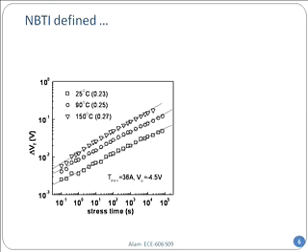Now, why did its threshold voltage change? Because as the hydrogens are diffusing away, you have more defects. Those more defects are catching more electrons. That causes a QF. Do you remember the QF and QIT? So it increases the QF and QIT. As a result, your threshold voltage changes, and therefore your current changes. So this tells you how much current change there would be.